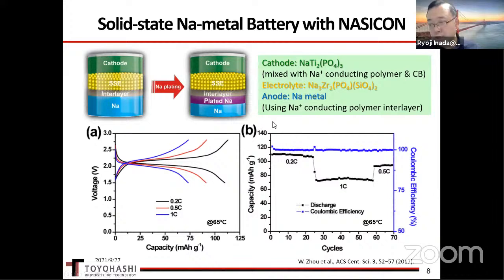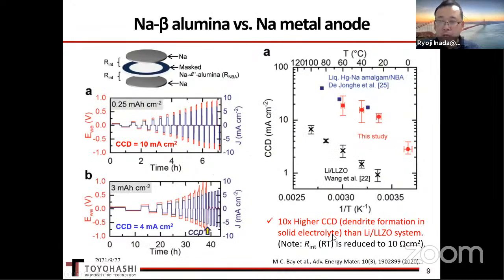As a result, this battery sample operates at around 2 volts and shows very good cycling performance at 65 degrees C. Of course, this is very basic research. The interface issues between sodium beta alumina and the sodium metal anode in the room temperature range are also investigated. When we achieve a sufficiently low interfacial resistance, below 10 ohm square centimeter, between the sodium beta alumina and the sodium metal anode, the sodium beta alumina symmetric cell has much higher tolerance for dendrite growth into the ceramic solid electrolyte compared to the lithium metal and garnet type LLZO solid electrolyte system. Although there are many issues to be solved for the practical use of sodium metal anode, this result indicates the possibility of fast charging solid-state sodium metal batteries in future.